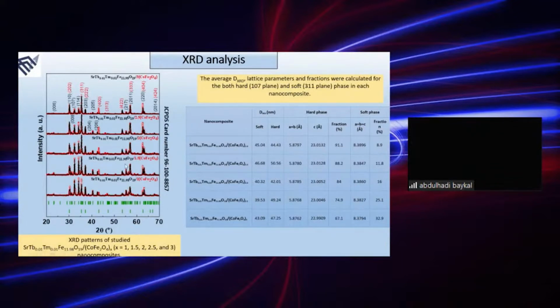For this purpose, we used Rietveld analysis. Okay, you see the X-ray powder pattern of each sample, 1, 2, 3, 4, and 5. We did Rietveld analysis, and then we did phase analysis like this, and there is no impurity. There is no peak that shows the presence of even a small amount of impurity. Then by using this software we can get some information. This information is given in this table on the right side. So we can easily calculate the crystal size of the hard and soft parts in each composite by looking at their major peaks here.